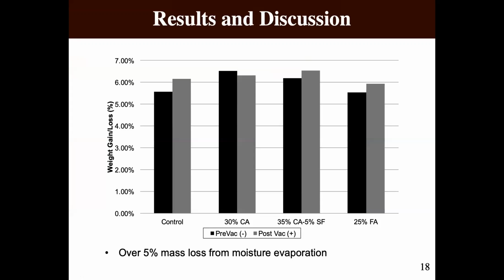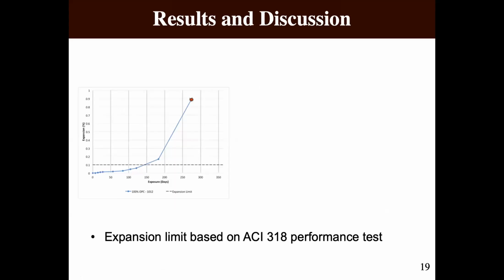So this is interesting data, showing you what happens when you dry out the samples. This is confirming that on the black, before vacuum saturation, you've eliminated about 5.5%, for instance, of water from the control. And then post vacuum impregnation, you have about 6% or so of moisture gain. In other words, this is what we assume to be the sodium sulfate solution being absorbed back into the sample. So it's confirming to us that we are indeed removing moisture, allowing the pore system to be emptied, and then filling those pores back up with the sulfate solution, right?